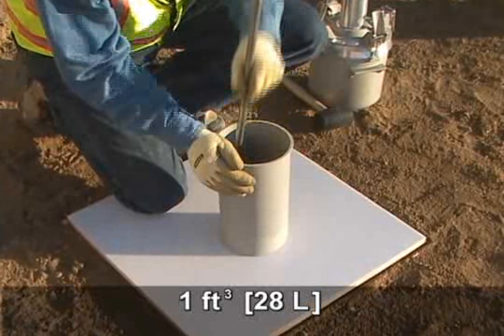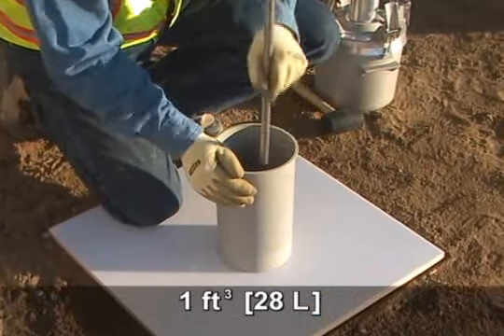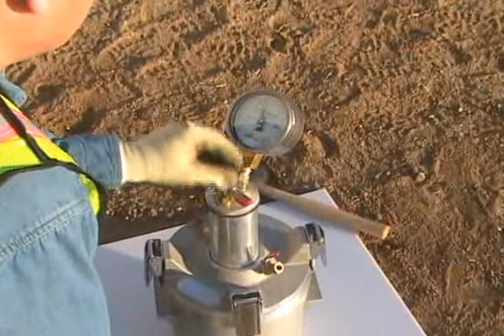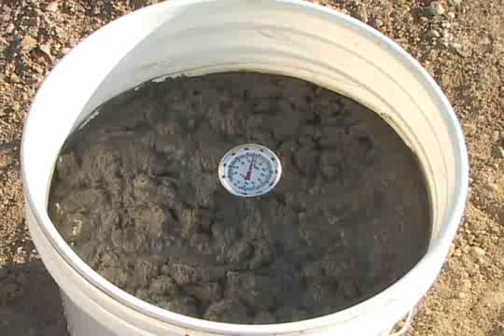When test specimens are to be molded, samples shall be a minimum of 1 cubic foot. Smaller samples are permitted when routine air content, temperature, and slump tests are performed.